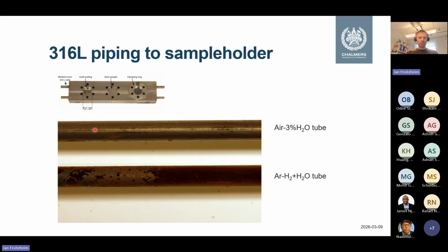When we did our first experiment, these are the stainless steel pipes, 316 steel, that lead to the sample holder. This tube had air on the inside, this tube had fuel on the inside. This is like 1 millimeter stainless 316 steel, and you see immediately this massive difference. And this is like 20 centimeters from any connection. So there is clearly, this is not leakage. This is going through the steel.